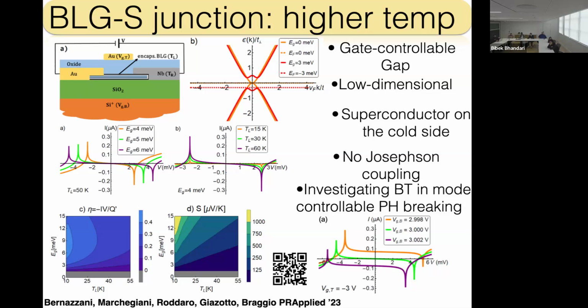And so you can compute the effect also in the presence of moderate breaking of the particle-hole symmetry. And you see that with the moderate breaking, it still works because it's a spontaneous symmetry breaking. There is another factor, the interaction in a normal metal, which is a huge amount of power that you have at your disposition. So even if you moderately break the particle-hole symmetry, you still have the effect. Okay.